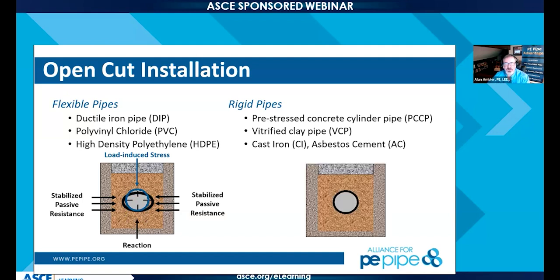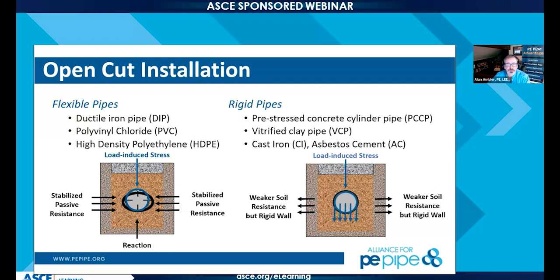Those are different from rigid pipes, where the hoop stress or strength is considered to be significantly higher than the weaker soil, in which case that pipe is tasked to direct all of the load that's on top of it to the soil underneath it. So it's interesting to note that even though the hoop strength or elastic modulus of HDPE is significantly less than ductile iron pipe, the interface it makes with the stabilized soil surrounding it makes a big difference.